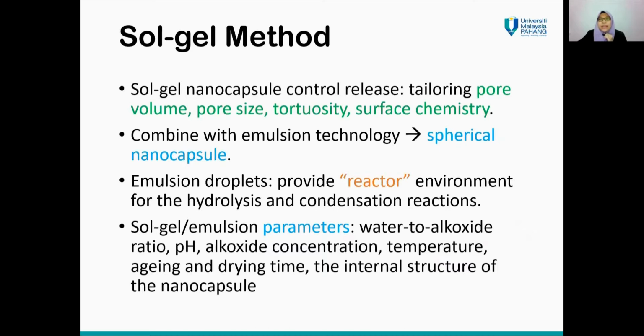Okay, so the nanocapsule is able to control the release profile of active species by tailoring the pore volume, pore size, tortuosity and surface chemistry. It is combined with emulsion technology to obtain spherical nanocapsule where the sol-gel molecular entrapment is carried out in or around emulsion droplets. In brief, the emulsion droplets provide a reactor environment for the hydrolysis and condensation reactions of the metal alkoxide. By controlling the sol-gel or emulsion synthesis parameters such as water to alkoxide ratio, pH, alkoxide concentration, temperature, aging and drying time, the internal structure of the nanocapsule can be controlled to ensure its effective performance for a number of applications.